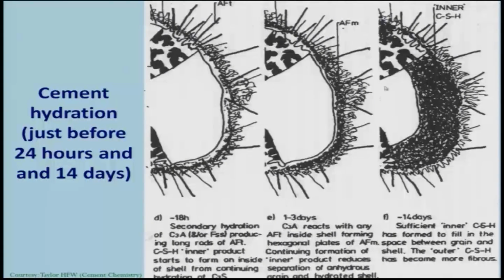Okay. So, what we can understand in the 14-day figure is that you have some portion of the cement grain that is unhydrated and some portion, this black color region, showing that the hydrated compounds are formed, and all these things happen as a solid state reaction, and water cannot completely get into the cement grain, and it can do so only through a process called diffusion.